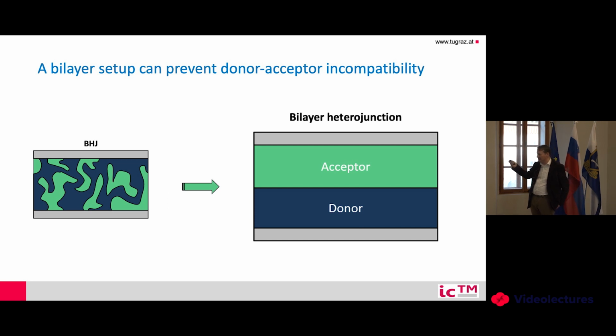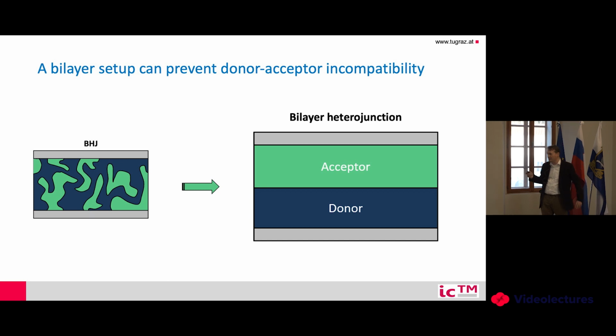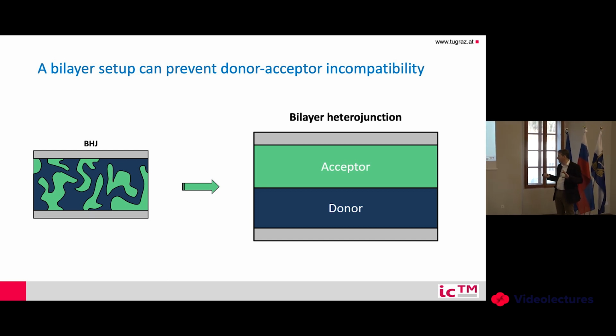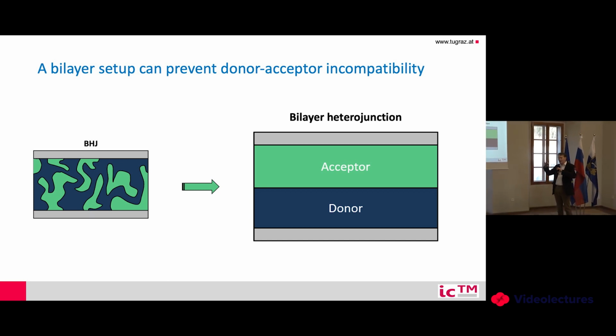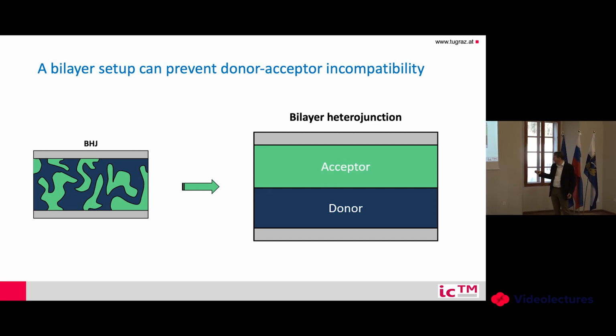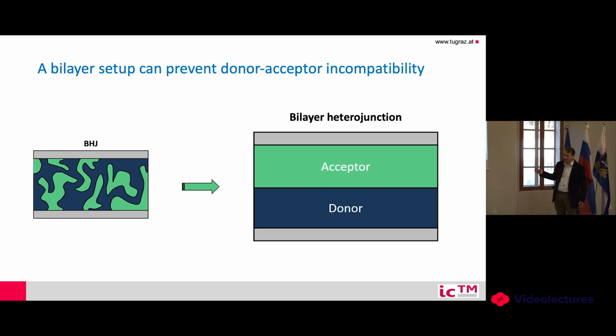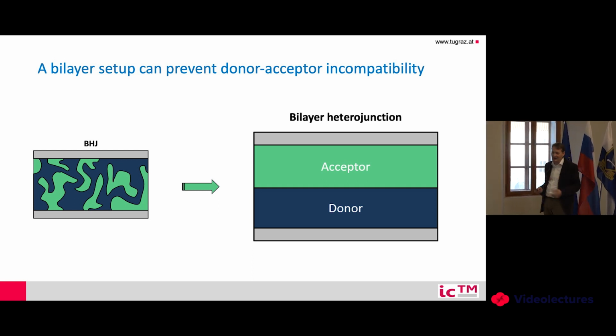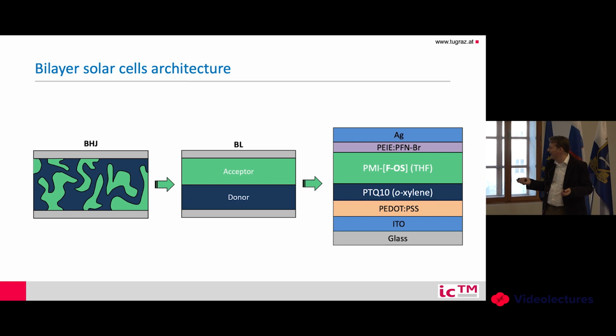The usual strategy is to use a bulk heterojunction. But in this case, if you have two different solvents, it's usually much better to use this bilayer approach. So we go back and say, okay, this bulk heterojunction approach is nice, but in our case it's better to have this bilayer approach. It's probably too ideal, because the surface is probably rough here, so you have an intermixing nevertheless in the surface layer.